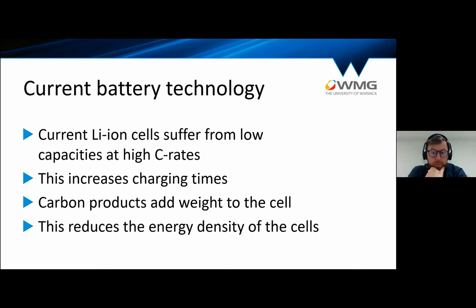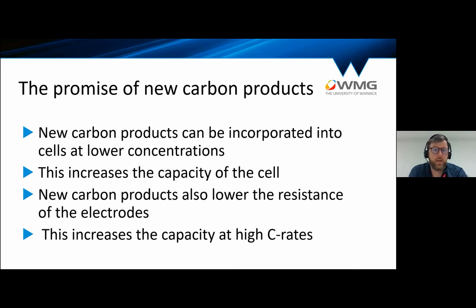So carbon products, again, can add weight to the cell. People are normally putting in these carbon products to give better electronic conductivity, and that then helps in terms of your discharge capacity and keeping the overall capacity of the cell up. But if you're putting more of this in, then you have electrochemically dead weight in there, and this then reduces the energy density of the cell. Because you have to have it in there to make it work, you'd rather have the minimum amount necessary in there to get maximum performance out of the cell.